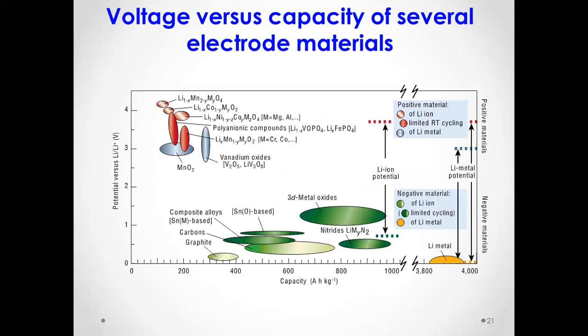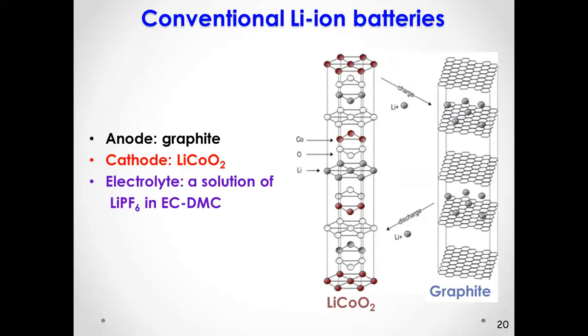Originally you will have 100. After certain cycles, maybe 100 cycles or 200 cycles, you could see you may have only half of the lithium ions. That's why when you buy a brand new lithium ion battery, it may support your application for 1 or 2 days. For example, if I make a 100% charge, I can use it for more than 1 day. But after 1 year or 2 years, you could see your batteries will not be stable. Even if you charge it, it shows 100% charge, but hardly half of the lithium ions are available for shuttling. The battery will get discharged within half a day or maybe less. So eventually you have to replace your batteries.